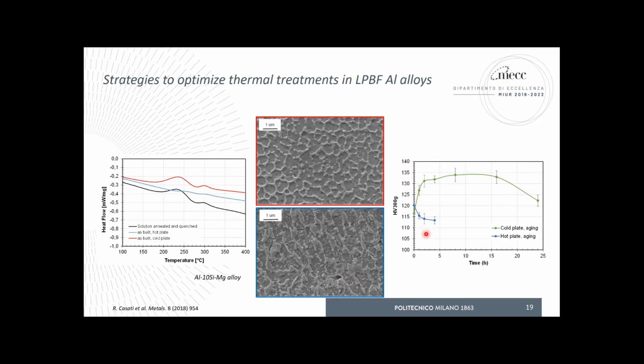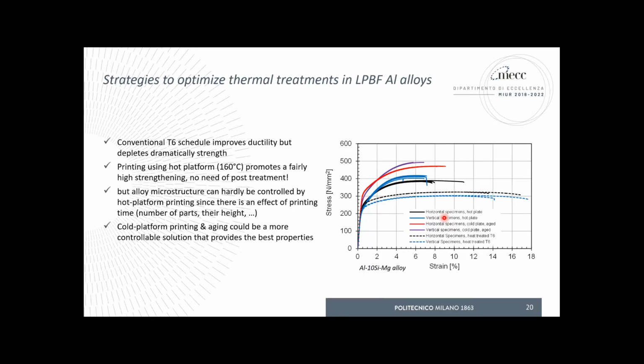But again, here on the right-hand side, we have the same information, if you want. The alloy produced by the cold plate, so no preheating, is able to provide quite significant increase in hardness during aging, while the hot plate samples do not show any aging. Indeed, they show stress relaxation and nothing else. Very last slide, and then we can skip to conclusion.